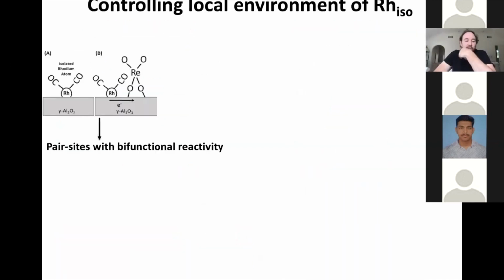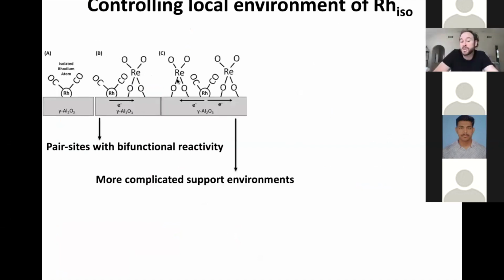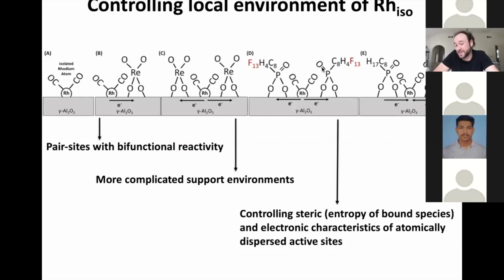So you can imagine many ways to increase complexity and functionality. You can imagine putting 2 different sorts of sites next to each other, maybe a rhodium and a rhenium. These sit in very different oxidation states. Maybe you could get one ligand to coordinate here and another to coordinate here, and you could have some bifunctional reactivity. Maybe you could completely change the support landscape and have a support that's multifunctional, alumina, rhenia, all sitting around our atomically dispersed rhodium. Or maybe you could do organic functionalization of the support, so you can do condensation of phosphonic acids, and here you can begin to control the steric environment around these atomically dispersed species, and we're working on all of these different avenues.